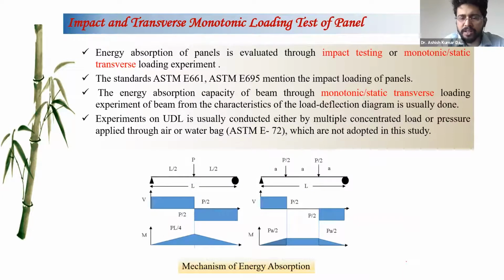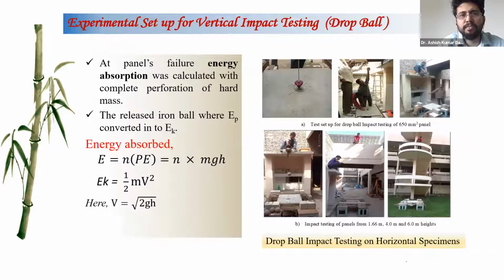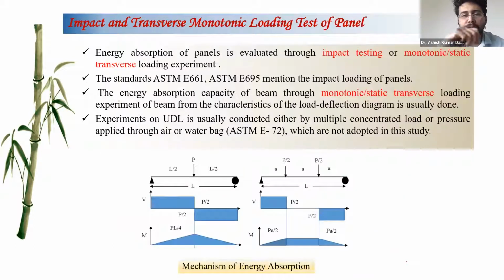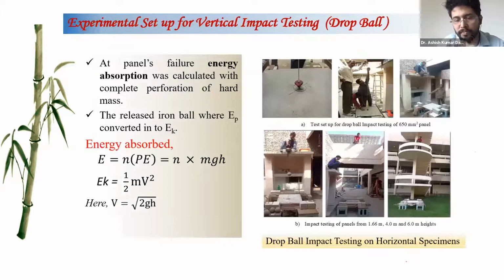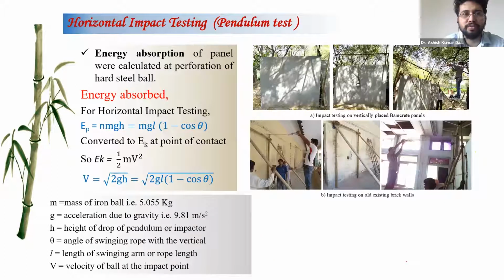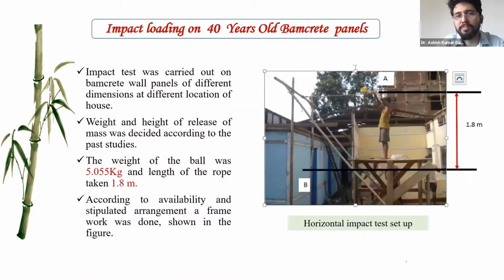So the impact test and the monotonic loading test, the static loading test usually, which we consider for the energy absorption capacity of this bamboo walling system. In both the vertical and horizontal impact testing with the hard body impact test, we conducted the test on the existing 40 years old bamboo walled panels.